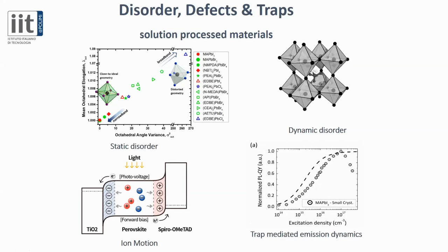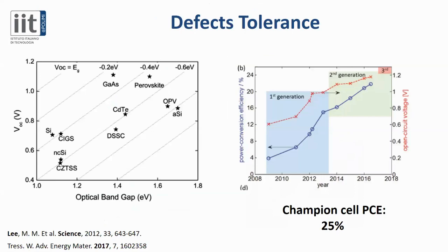Nevertheless, since the first application in a solar cell, these materials show very little losses, so very impressive primary optoelectronic properties. Direct band gap, very long diffusion length of carriers, very good light absorption. And here on the left, I'm showing the VOC of solar cells as a function of the optical band gap. So this is a way to roughly evaluate the importance of losses in solar cells.